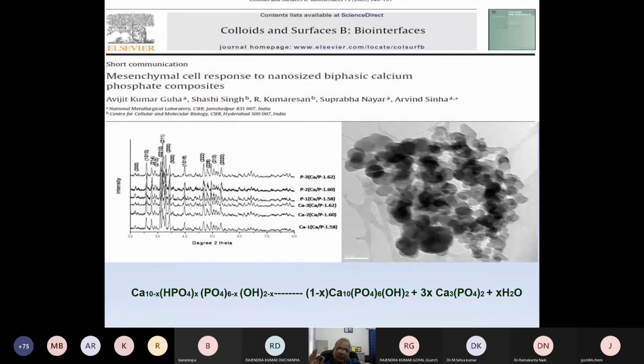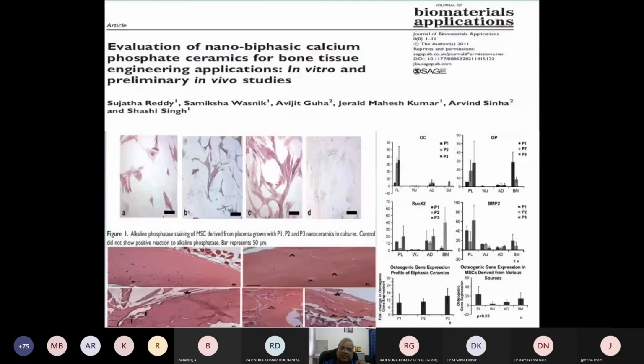So what we thought, we know that beta calcium phosphate has similar properties. So if in material we can produce this sort of nanocomposite of the two phases, we will get the strength as well as the bioactivity. So we could produce it biomimetically in nano size on a large scale. And then we again gave it to CCMB.